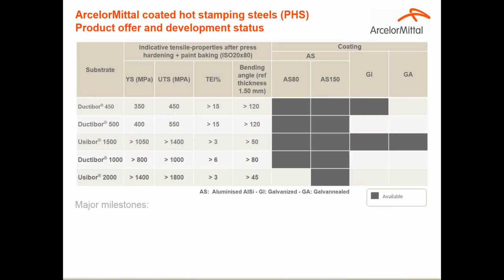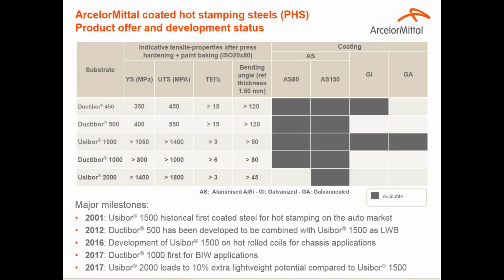Looking in more detail at the product offer, as just said, we saw the first application in automotive of coated steel for hot stamping 15 years ago, a bit more. After that, the demand increased drastically. And to follow this demand, new grades have also been developed with different mechanical properties that are shown in this specific table. Not focusing on the mechanical properties, which are quite easy to read, with different yield strength and UTS levels, we see also elongation and bending angle.